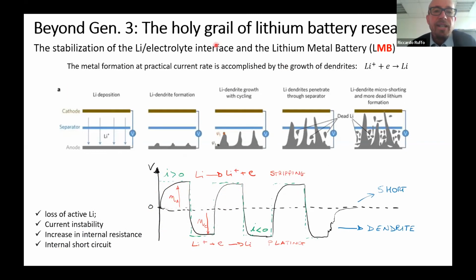So the holy grail of lithium battery research in producing better batteries is the use of metallic lithium, which is not included in the current technology, what we call lithium metal batteries. Lithium metal batteries are currently widely used in primary systems, so not rechargeable systems. The reaction is very, very fast. It's the oxidation of lithium to give the lithium ion. But the problem is the reversibility of that.